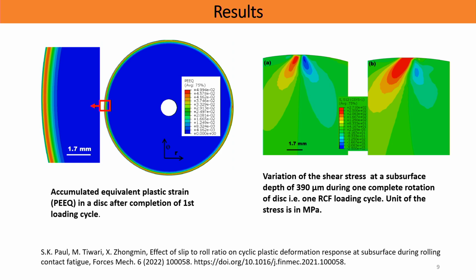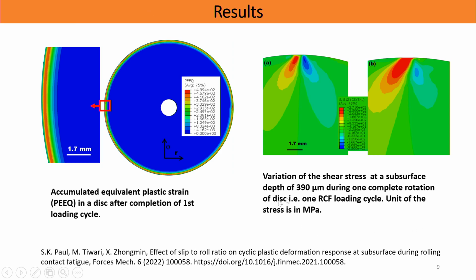So if you go through the website of this company, you will see 4 or 5 places in which IIT Patna is there. So we have these stresses, and because of sliding, we saw what was happening. The symmetry of the subsurface shear stress was changing, right? So this is shown here also. You can see this is 0% sliding, it's pure rolling. This is 5% sliding, and you can see that this is more the tensile with respect to the compressive. Okay. So this symmetry which we were seeing in the simulations, this is also simulation just now, very difficult for us to see in the experiment.